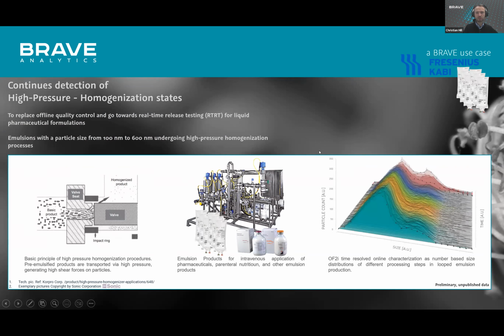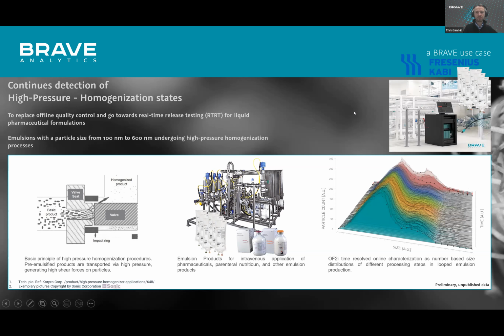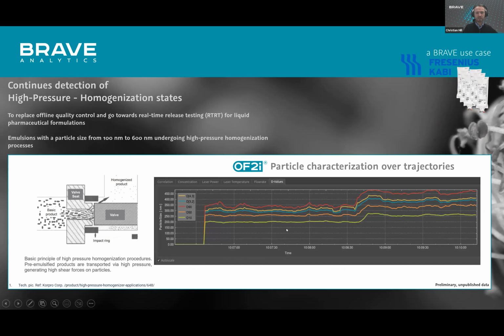Here you can see, for example, that we can really deliver concentration over size over time. And as soon as something changes here, for example, in this area, a processing step changed, we can directly see this with a time resolution of every 10 to 15 seconds, when you get the full number-based size distribution. As process feedback, we give so-called D values, and they are coupled back into their production line, so they can act on those signals.